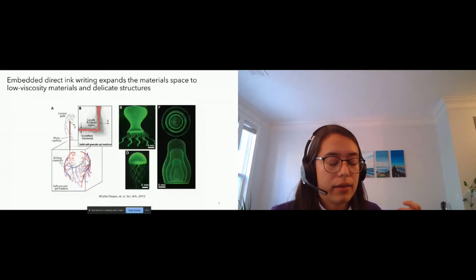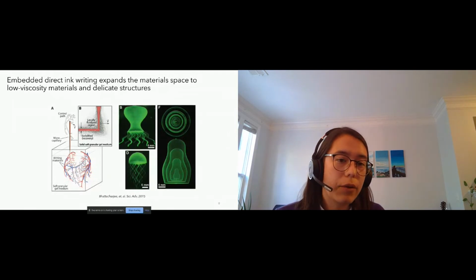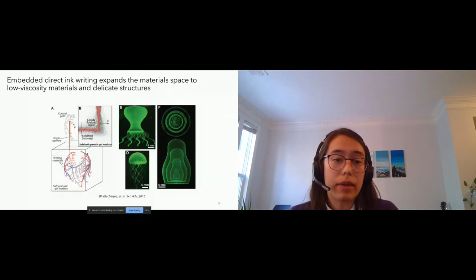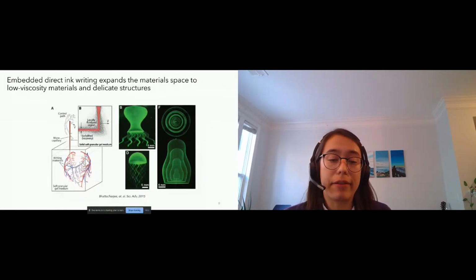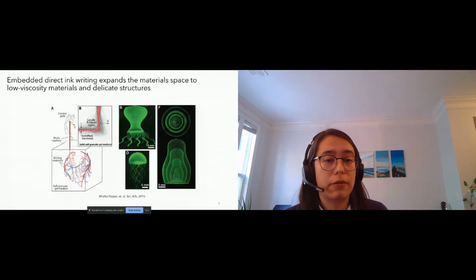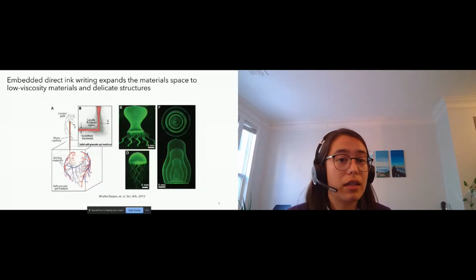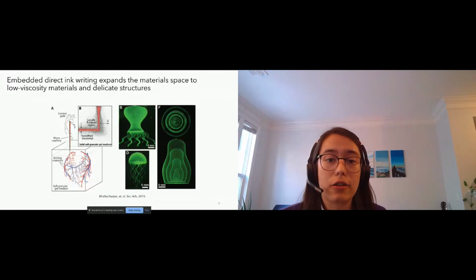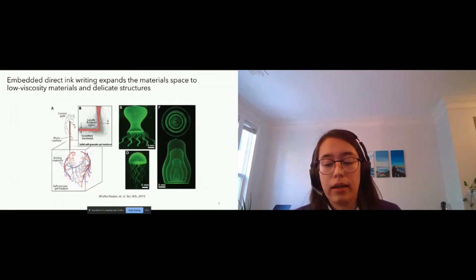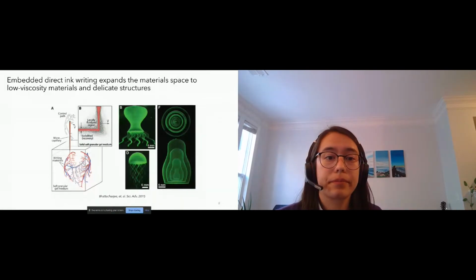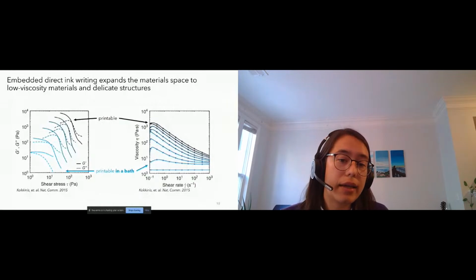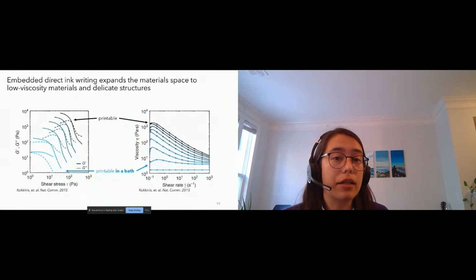Because these materials have a yield stress, they'll behave like a liquid when the nozzle's moving through them, and that'll allow the nozzle to move. But they'll behave like a solid after the nozzle has left, so they'll hold the form of whatever you printed. This means we can expand the available material space into low viscosity materials, and we can print thin-walled structures and delicate structures, because we don't have to worry as much about the properties of the ink when you have that extra support available. After you're done printing, you can remove these parts from the bath either by scooping them out or using dissolution in a buffer. So those blue inks, those low viscosity inks, are now going to be printable as long as we use a support bath.